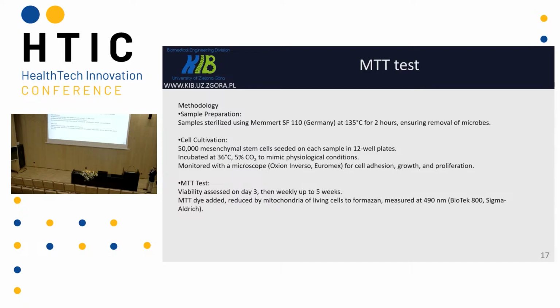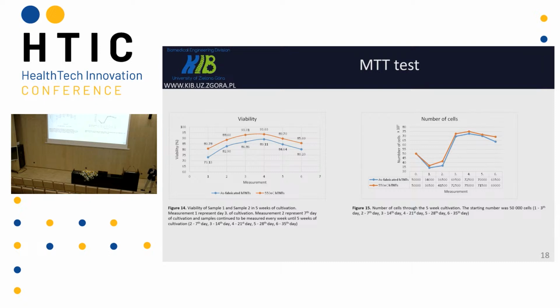Then we seeded 50,000 mesenchymal stem cells, and we carried out the measurement from 3 to 5 weeks. When we got the result, we were positively surprised because the viability of stem cells on this surface was very good, and thermal modification improved this parameter. Also the proliferation, or the number of cells, was increasing, and it was also a very satisfying result.